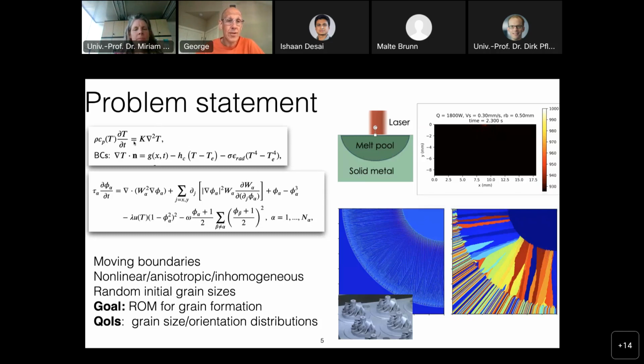The melt pool physics can be very complicated, but here we're going to use just a nonlinear heat equation, which I'm going to discuss shortly in a subsequent slide. And then we're going to use a phase field in order to capture the microstructure formation. So here you can see what are called dendrites, but essentially these are crystals, and every crystal grows in a specific orientation. This is the crystallographic orientation. And then the interface between crystals and the different orientations creates stresses, and then you have to go to crystal plasticity to take these statistics down to a finite element crystal plasticity code, and then we'll do some kind of averaging to find effective material properties, yield surfaces, etc. So that's the workflow.